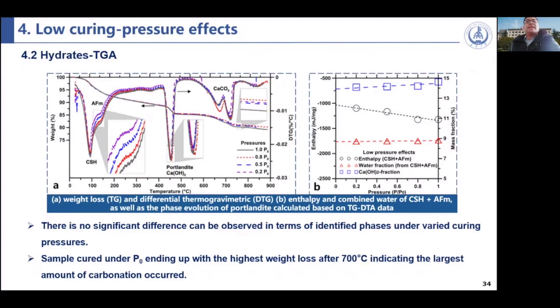This is what we got, the enthalpy and the mass fractions during the TGA. We can also see very slight differences in the water fractions from this part, but the curve here is different, and we can also see the Portlandite is also different, especially it is reduced by the lower curing pressure.